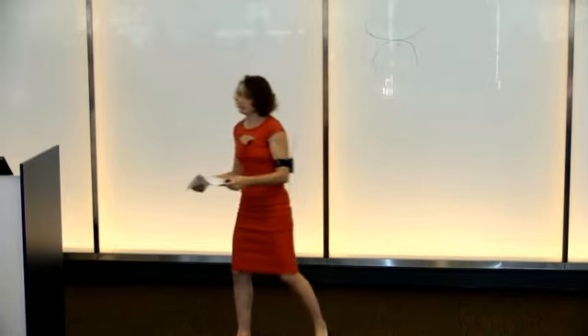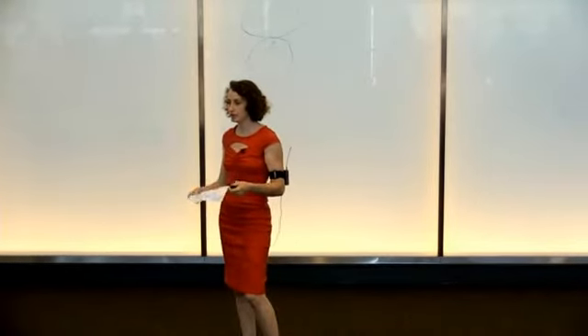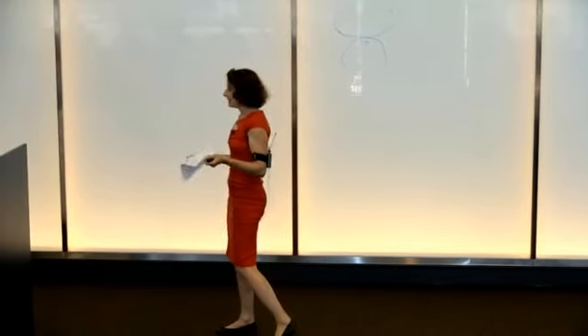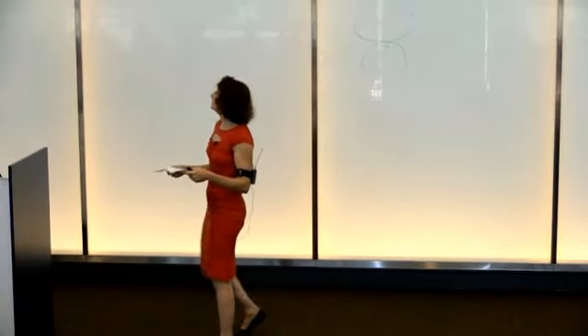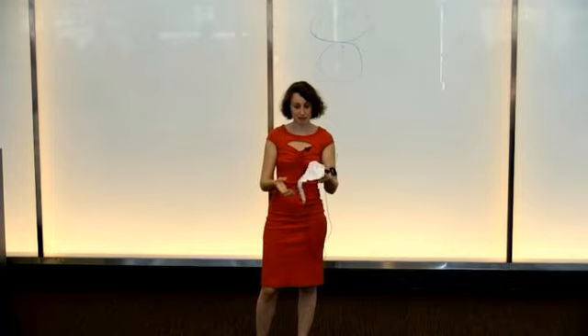Hysteresis. So our system has memory, and a way to show and study memories is to check if it has hysteresis. This means that the current shape is going to depend on the history of what I did to my sheet. And in order to study hysteresis, what we did was to take the sheet, fix 3 of the nodes. So one is going to be fixed completely, one is going to be able to go along a line, and one is free to go on a plane. This is just to kill the translations and rotations, degrees of freedom.